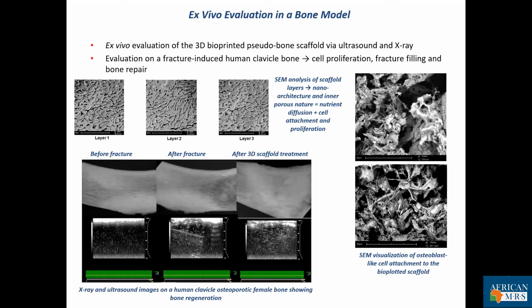Ex vivo evaluation was undertaken in a bone model, and various techniques were employed to analyze the success of this approach via microscopy, ultrasound, and X-ray. So you can see from the SEM images, you have your nanoarchitecture and your porous nature that's created by your scaffold, enabling your nutrient diffusion, cell attachment, and proliferation. X-ray and ultrasound images were done on the human clavicle to show the actual healing from before the fracture to after the fracture, and following the successful 3D scaffold treatment. SEM also showed the osteoblast-like cell attachment to your actual bioplotted scaffold.